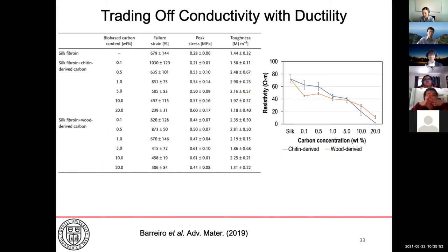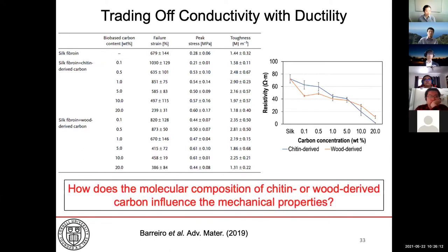Now, by adding such small amounts of bio-based activated carbon will dramatically increase the ductility and the toughness of the films. But of course, as we added more, we trade off the properties between carbon and silk until the film becomes very brittle, but very electrically conductive. And therefore, we were actually curious to know, how does the molecular composition of chitin or wood-derived carbon influence the mechanical properties?